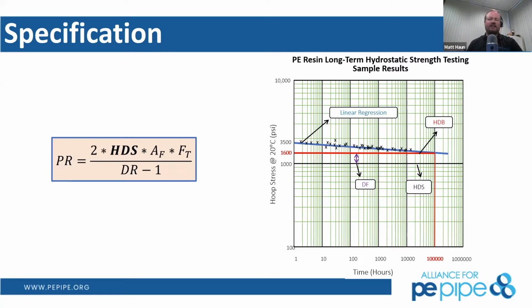So these data points are used then to draw a more highly confident line for realistic operating conditions, for example, 73 degrees Fahrenheit as its base, to predict that behavior over the long-term stress. And so with the mathematical confidence of that trend line, we can develop a hydrostatic design basis for each of the resins. And so we apply a design factor to that HDB that bridges the differences between lab conditions and real life. So that means resin and pipe manufacturing, shipping, handling, storage, installation conditions, temperature fluctuations, sky's the limit.